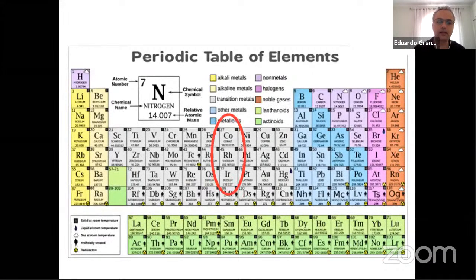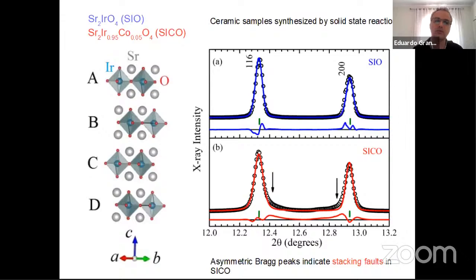So let's look again at the periodic table of elements. If you look at the elements which are in the same column as iridium, which are rhodium and cobalt, these are the elements I mentioned before, chemically similar to iridium. So that's where we may have a substitution that may induce an electronic level very close to the Fermi energy. So we tried rhodium or cobalt substitutions. Actually, rhodium substitutions were attempted before, and they induce a metallic phase. So it kind of overshoots the doping, and it's already known that the rhodium substitution leads to a metallic phase. So we tried the cobalt substitution, and we studied that with some techniques. We studied that first.